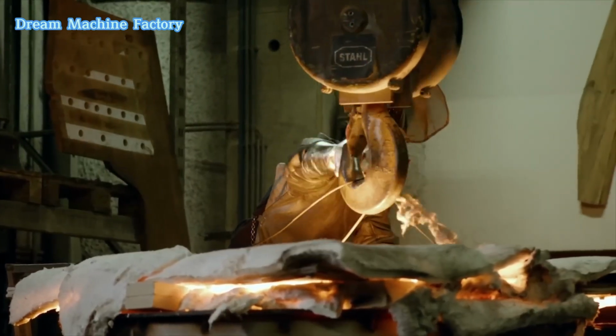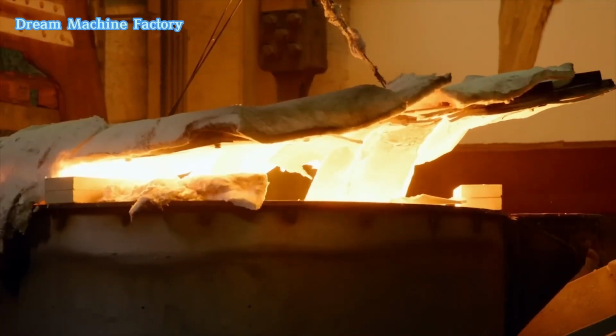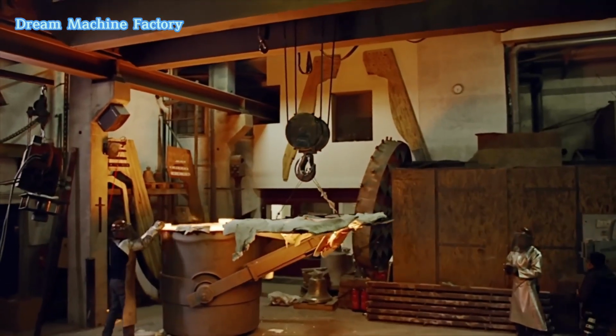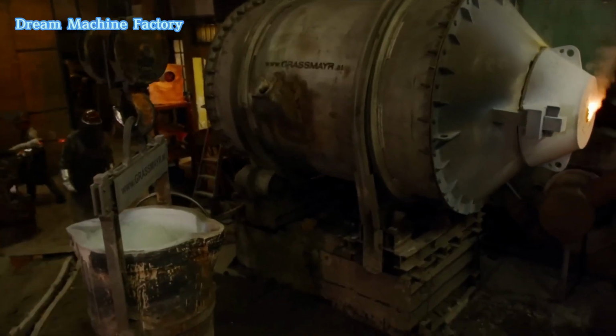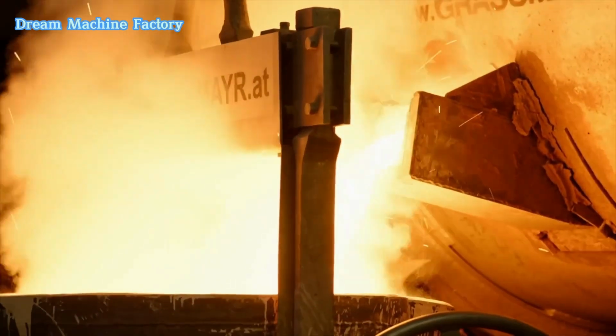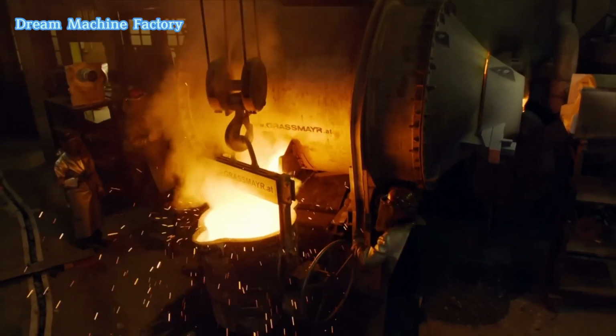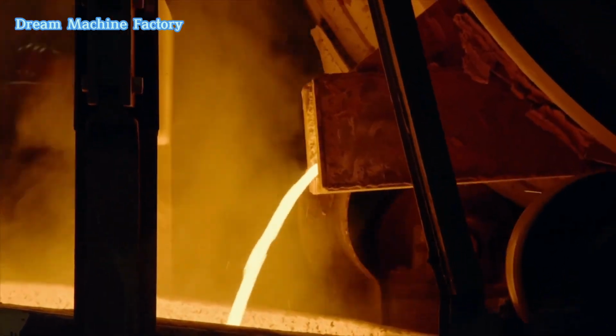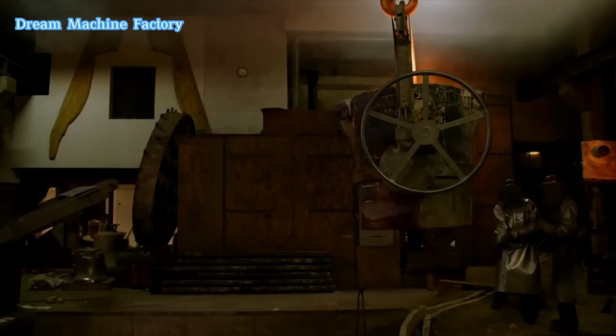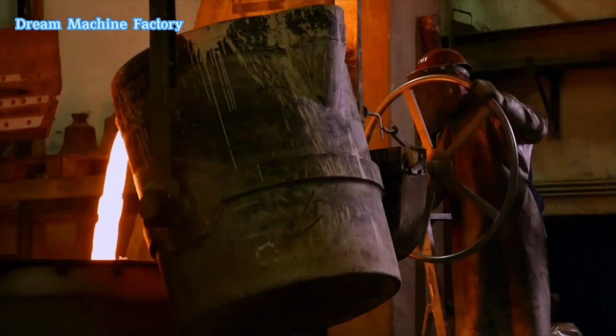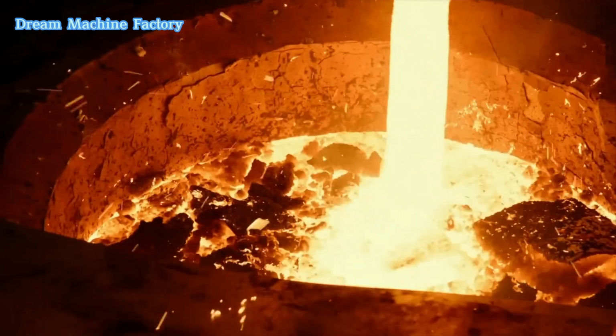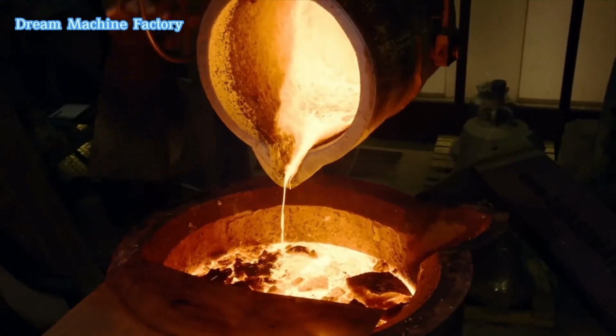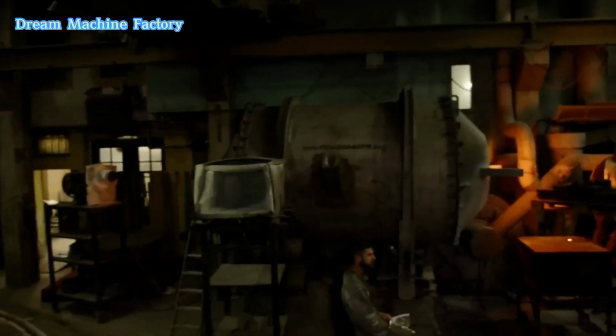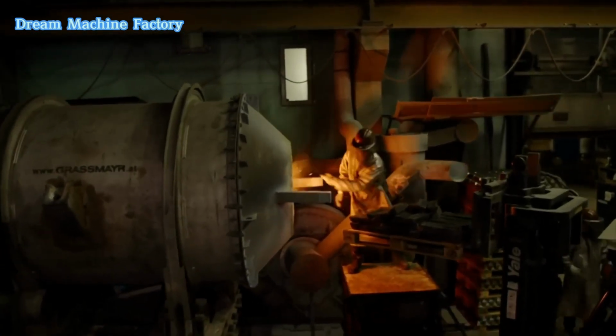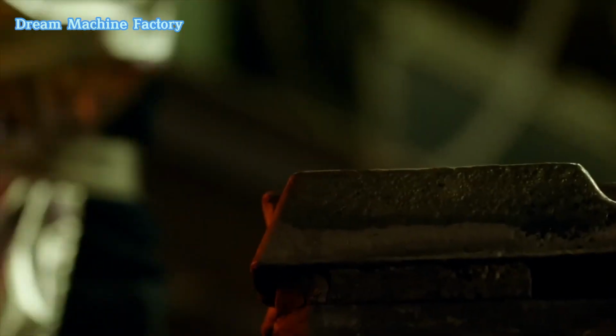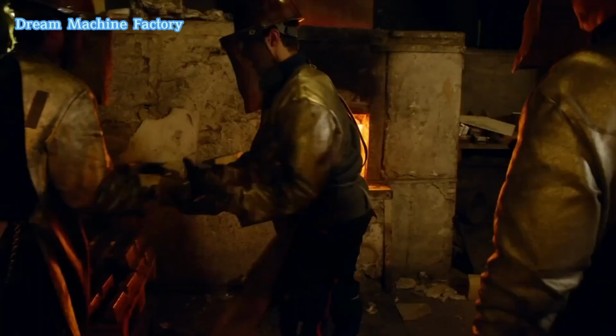Bells are traditionally cast using a bronze alloy composed of approximately 78% copper and 22% tin. This specific mixture provides the best balance of durability and acoustical properties. In some cases, small amounts of other metals, such as silver or phosphorus, may be added to enhance the tone. The metal is melted in a furnace at extremely high temperatures, reaching up to 1,100 degrees Celsius, 2,012 degrees Fahrenheit. This process can take several hours, as impurities must be carefully removed to ensure a high-quality cast. The molten metal is then transferred into a pouring ladle, ready to be introduced into the mold.